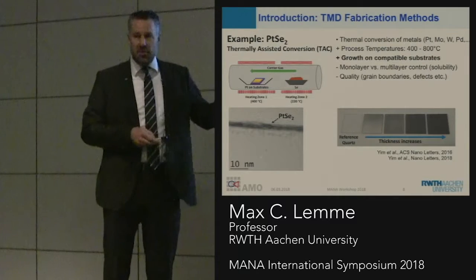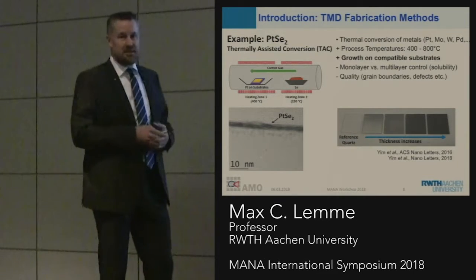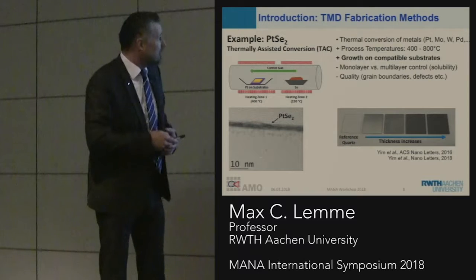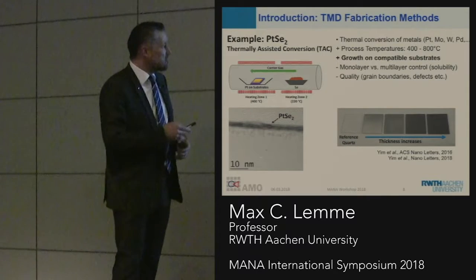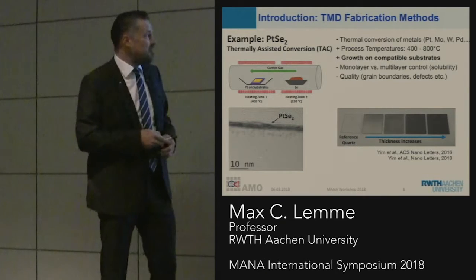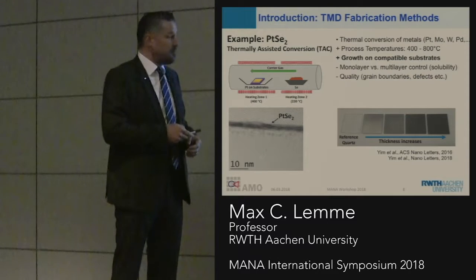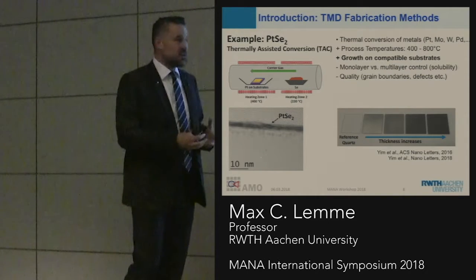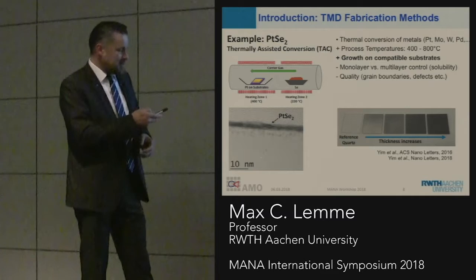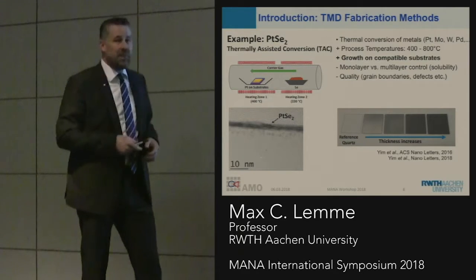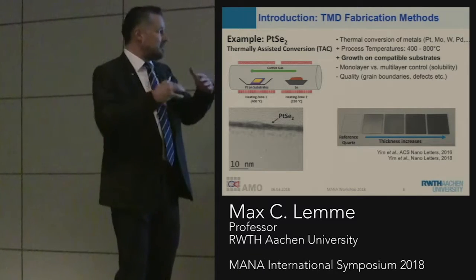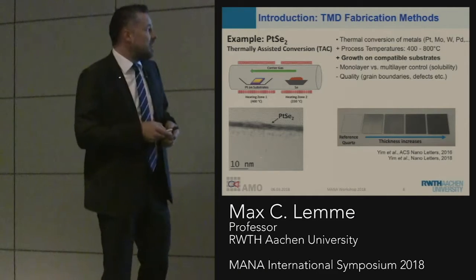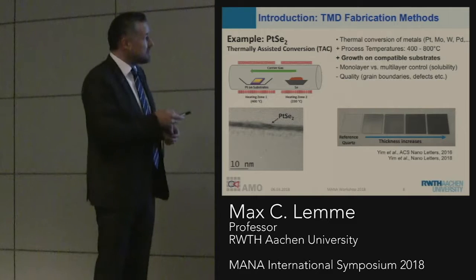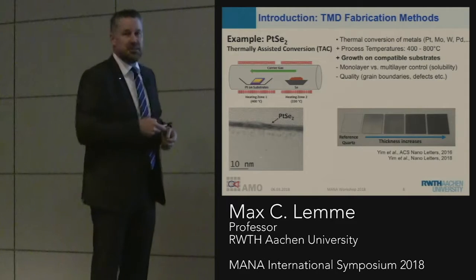Now, we can also grow 2D materials with this kind of method. In this case, I'm talking about thermally assisted conversion, which is a derivative of the CVD method, where we start out with a metallic surface and then introduce a material. In this case, the metallic surface is platinum, and we introduce selenium, and then it intercalates and forms these layered 2D materials. This is typically done at temperatures between 400 and 800 degrees C.